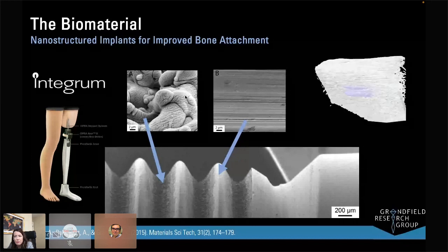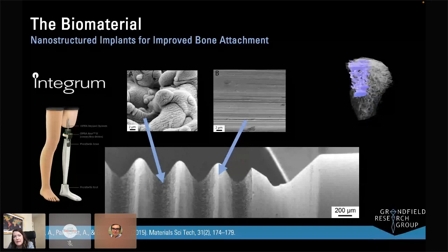When these implants were removed in preclinical studies, we found that the force to remove this implant with modification was 150 times higher than to remove an implant that had no modification and was smooth. So we really wanted to understand what is it about this nanoscale structure that's improving osseointegration, or this contact between bone and implant, and causing these high values of removal torque.